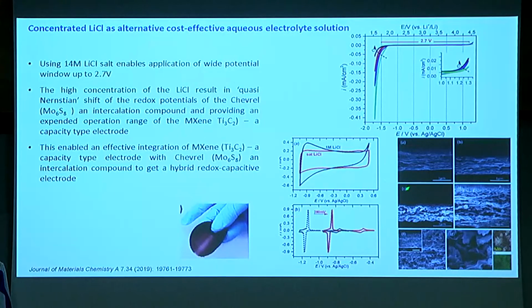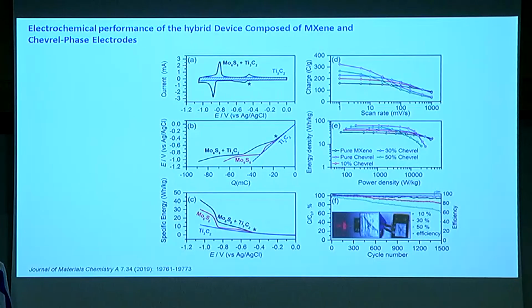So we take advantage that MXene is a 2D material with good electrostatic properties, and we encapsulate Chevrel phase particles between the MXene sheets, and we get a very nice, flexible, and freestanding electrode without a current collector. So here you can see the performance of this system.